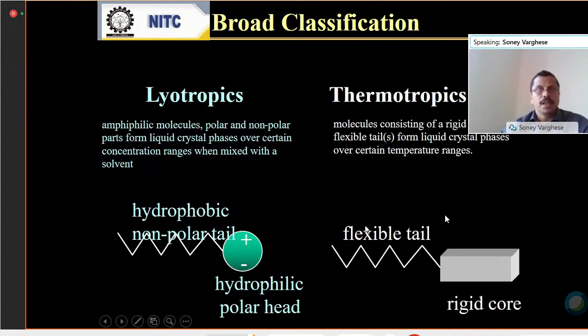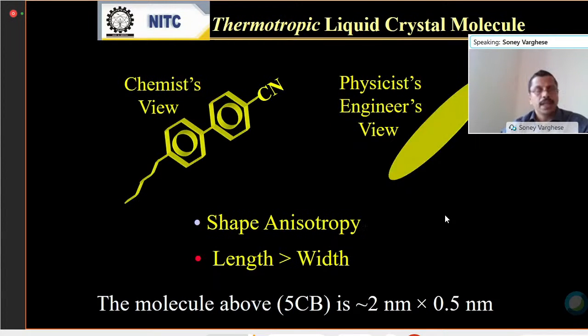If you take a simple liquid crystal molecule, this is one of the very basic examples, and you can see that this is basically two phenyls. So it's a biphenyl structure, right? It's a cyanobiphenyl, and you can have a tail structure also. Basically, you can see there's a polarization in this molecule. You have a negative side on the cyano side, positive side on the alkyl group, right? So basically, there is a charge separation, a permanent polarization, you can expect in such molecules.